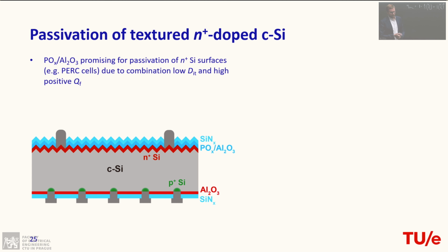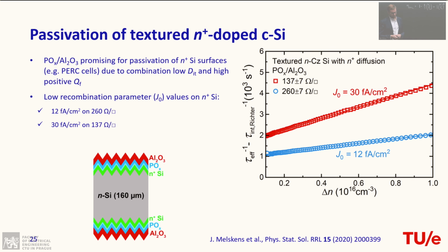Now, what would this look like in devices? As I already said, you can insert this stack maybe here on the front side of your PERC cell. We did not get to the point that we really tested this in real devices, but we got quite close. So we first wanted to establish whether you can passivate heavily doped surfaces, this N+ region that you find in PERC cells. Then you see different kinds of doping levels as expressed by the R-sheet value that you see over here. We have a lowly doped surface and a more heavily doped surface. In both cases, you can end up with quite low J0 values, meaning that it is interesting indeed to use this on the N+ surfaces. And what do these values now really mean? Because it's a bit hard to just guess it like this.